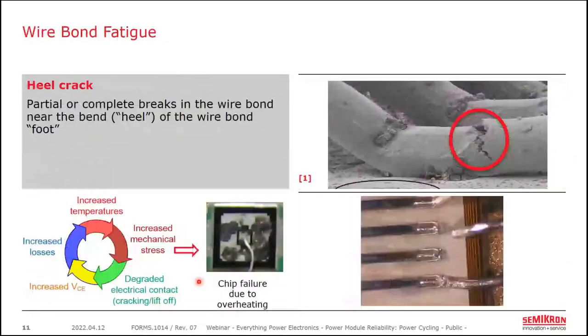At the beginning of this presentation, I described that bond wire foot and pointed out the heel, and here's why. As a bond wire and chip heat and cool, everything flexes, and a common point of failure is near the bend just before the bond wire is welded to the topside chip metallization. This mechanical fatigue starts as a crack, which increases the electrical resistance, which causes a higher voltage drop, which causes additional losses, which causes more heating, which increases the stress. And I'm showing this here as a cyclical process that starts to accelerate once it begins.